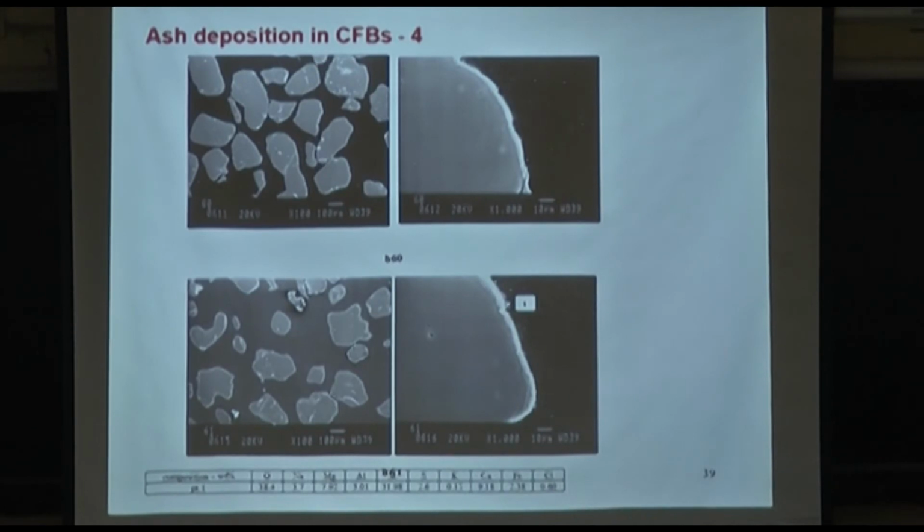So they were collecting the sticky material on their surface, but because at the same time they were also finer, they were moving away from the bed. So the bed agglomeration could be managed that way. So that's one option that we suggested. We tried that. Everyone was happy, so we stopped at that point. But there could be other measures as well.